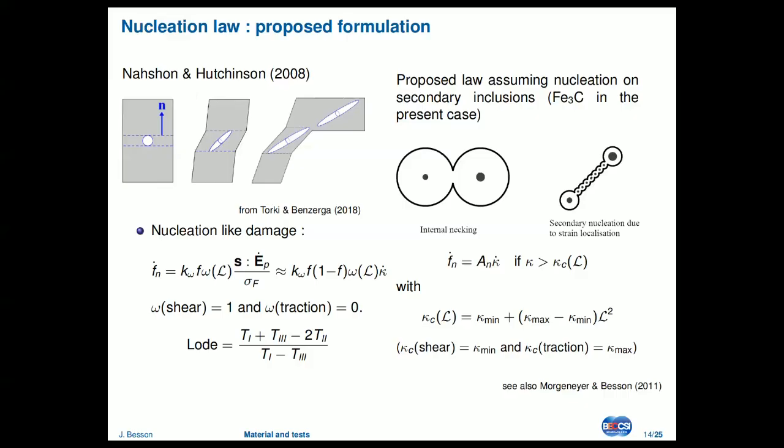I won't touch it. So we say that when we reach a critical strain, you will start to have carbides breaking and creating damage. Okay, well, that's a good idea. Let's try. No way, we couldn't have a good match between CT and SENT. We really tried hard.